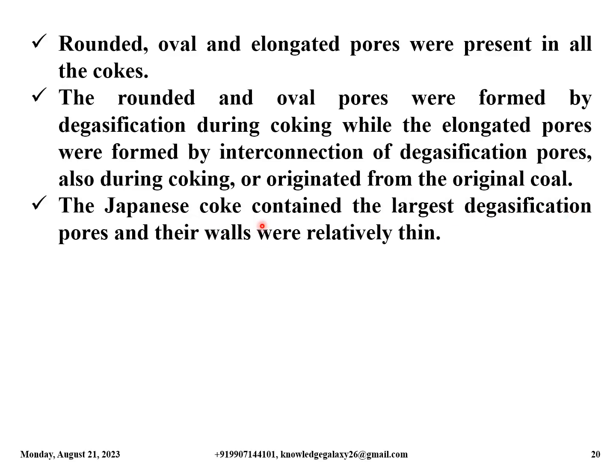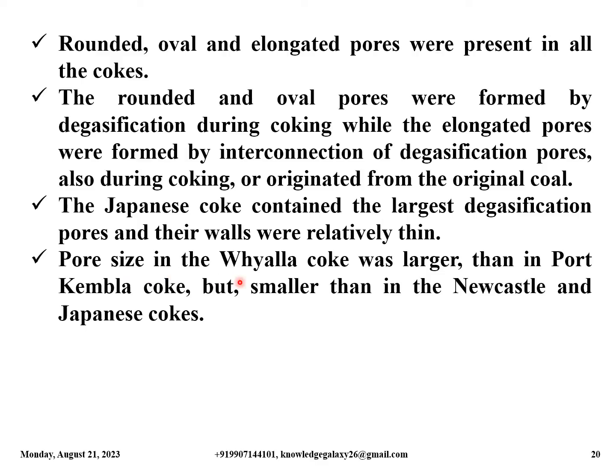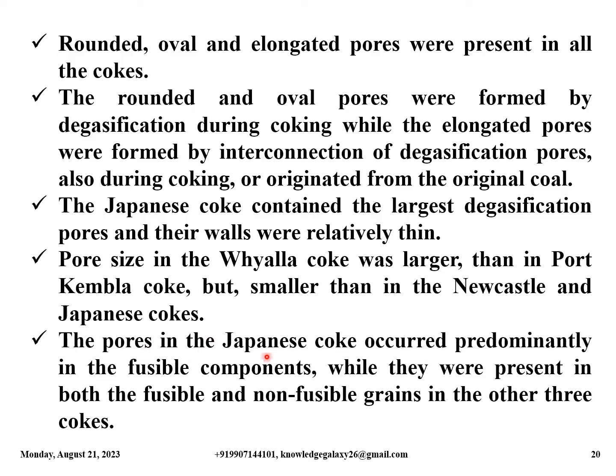The Japanese coke contained the largest degasification pores and their walls were relatively thin. Pore size in the Whyalla coke was larger than in Port Kembla coke but smaller than in the Newcastle and Japanese coke. The pores in the Japanese coke occurred predominantly in the fusible components, while they were present in both the fusible and non-fusible grains in the other three cokes.